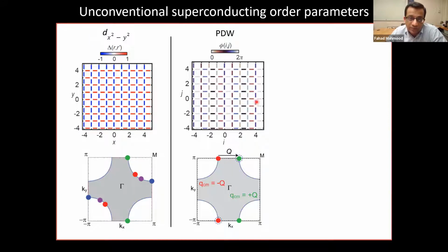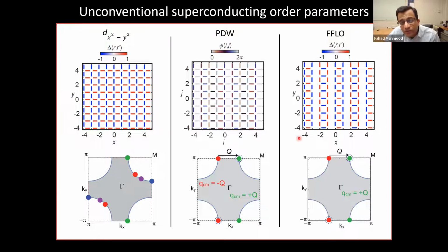We wanted to contrast this with what happens with a pair density wave, where the phase of the superconducting order parameter is now modulated as a function of space. In momentum space, that looks like pairing now occurring between these green points, or these red points. Okay, so now your Cooper pair has some finite momentum. In the FFLO phase, where the gap looks this way in real space, the pairing occurs only between these 2 points in momentum space, but not the red points. Okay. So what experimental technique can allow us to distinguish between these 3?